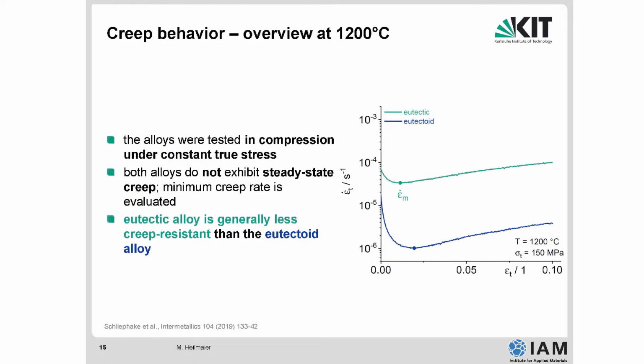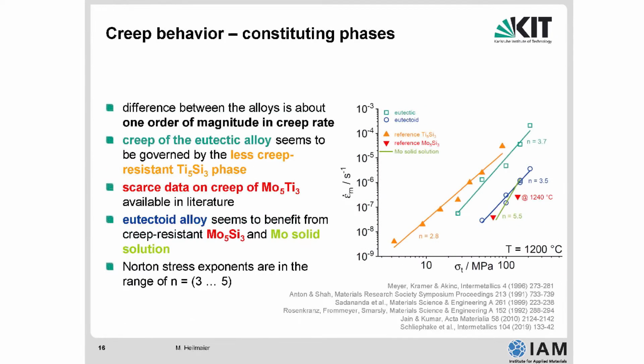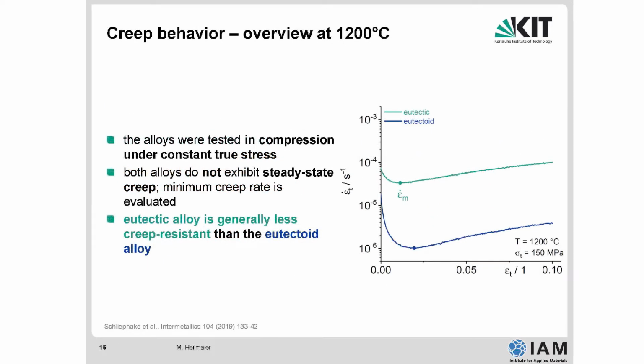So we need small plastic strains and low strain rates. So everything which is very much down low here is good. And the bad news here is that the eutectoid alloy, the one which is not oxidation resistant, is good. The eutectic alloy is not so good. Okay? This you can plot in a different way here. I've shown you all the experiments which we made. So each data point reflects one creep test at elevated temperature, 1200 C. And here we plotted the minimum strain rate, this point here or this point there. So this is the slowest creep rate we can have. It's a predominant data point here in this creep curve.